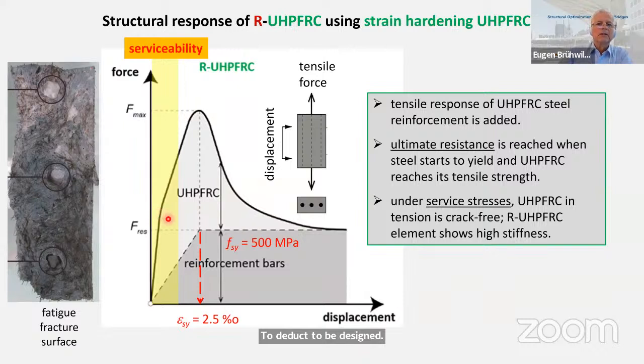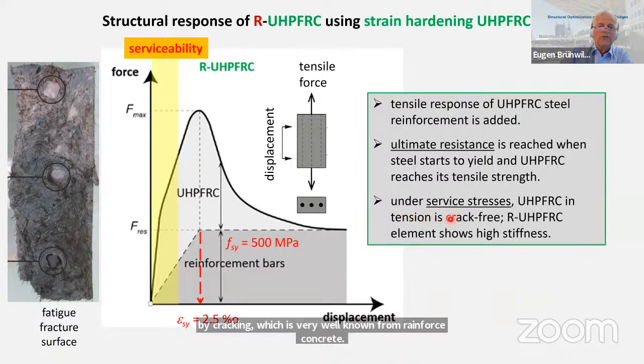Since we are working with lightweight structures, the serviceability limit state is very important. And the significant performance of our UHPFRC is actually the very high stiffness under service stresses here. Since we have no loss in stiffness by cracking, which is very well known from reinforced concrete, we have a crack-free situation. The elements have a high stiffness.